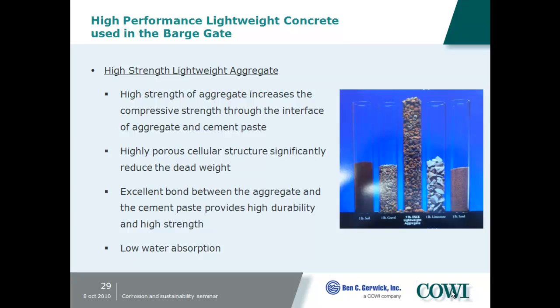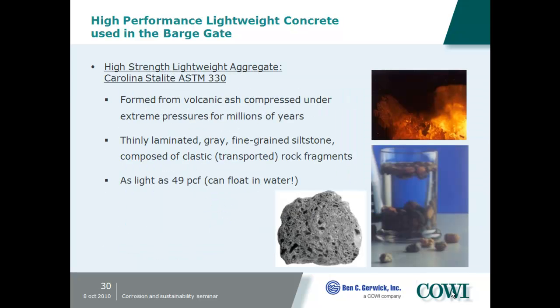So again, we used the Stalite lightweight aggregate. It is high quality. It's comparable with the strength of the cement. When it fractures, it goes right through the paste and the aggregate, whereas with standard weight it often goes around it. So that means that there's less cracking. So even under operation, there'd be less cracking occurring, so less avenues for chlorides to get in.